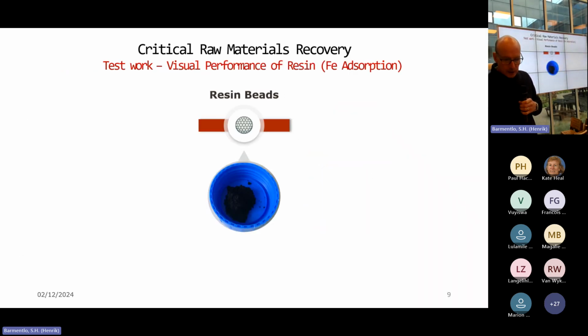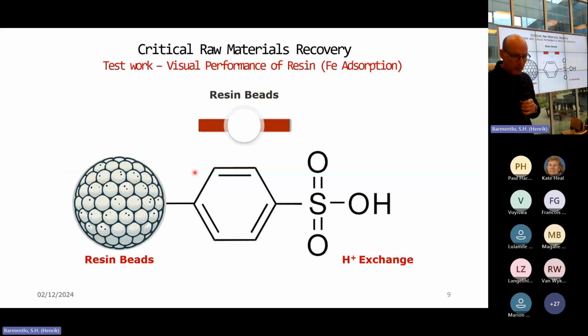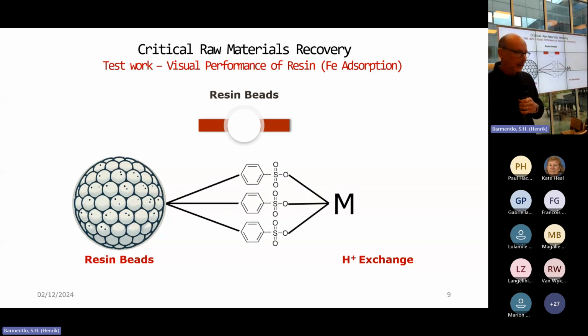And what does it look like? So that's typically what our resin beads look like. That's in a shot bottle cap, little black resin beads. And what it actually looks like is a sulfonic acid group attached to this bead. And what you're able to do then is this H+ atom over here is typically what you strip off the resin and you replace that with a metal. I don't know how much ion exchange you've done. And that's an M+, H+ exchange. And if you've got M3+, for instance, you would have it doing something like that. So you'd have triple the activation and you remove that.